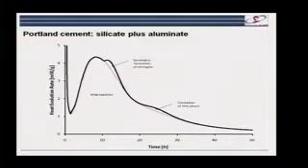So that's alite. And then if we go from alite to cement, you see that it's really pretty much the same. The scales aren't quite the same down the bottom here. But we've got two extra little reactions here. These little bumps are due to the aluminate, and we get two reactions. First of all, we get a second formation of ettringite, and then we get formation of AFm phases.